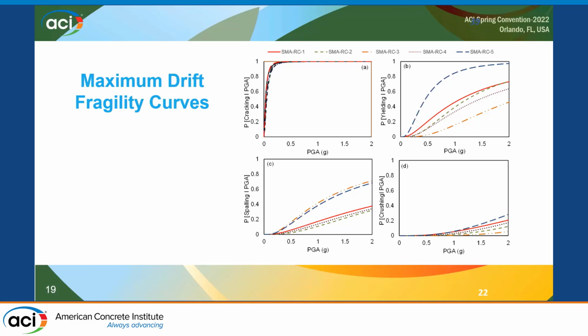But when we look at figure C, that is the spalling, we can see an interesting behavior. In the spalling damage state, SMA-3 has the highest probability of damage. In figure B, we can see that SMA-3 had the lowest probability, but in terms of spalling, SMA-3 has the highest probability of damage, and SMA-5, which had not a good performance in terms of yielding, performed better in terms of spalling. This can be attributed to SMA-3 having the lowest drift limit before entering the spalling damage state. This might be the reason for this.